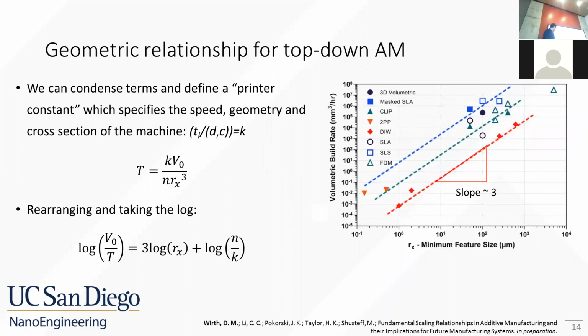And we see that the slope of 3 is coming from the cubic relationship of minimum feature size. Furthermore, we can see that the y-intercept of this plot is coming from the number of simultaneous deposition paths and some constant representing the geometry and the speed of the printer.